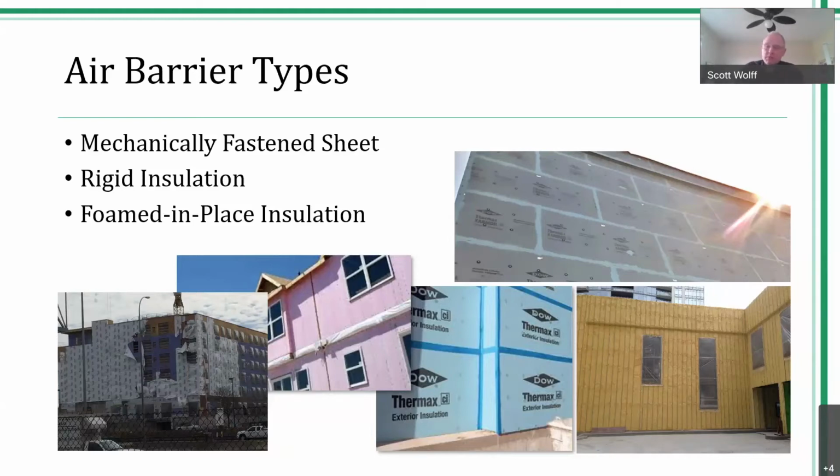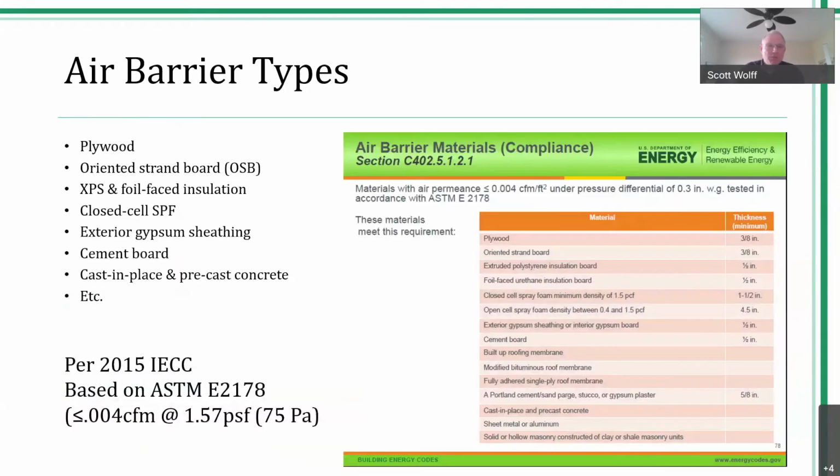Foam conforms to irregular shapes, and the only exception of its compatibility I would question would be silicone type air barriers and self-adhering vapor permeable sheet air barriers. So I would check with the manufacturers on that, but virtually every other type, the acrylics, the STPEs, the self-adhering modified bituminous sheet air barriers are generally very compatible with this, irrespective of manufacturer.